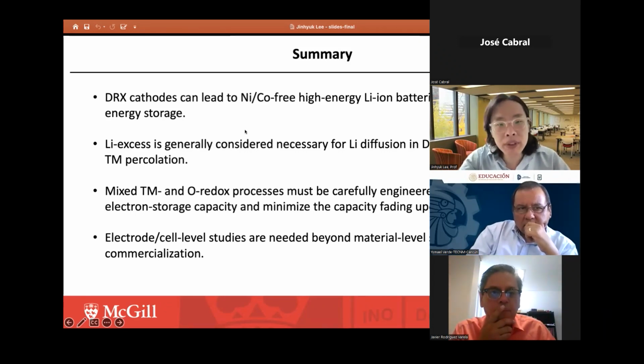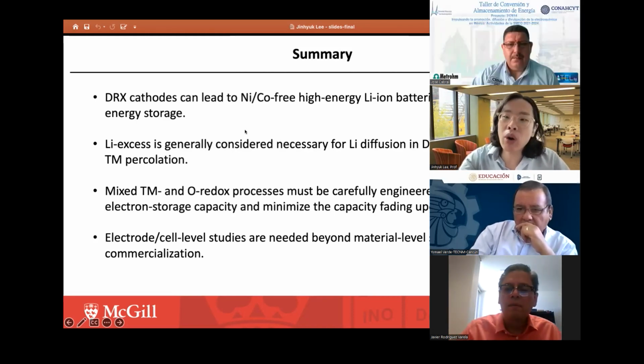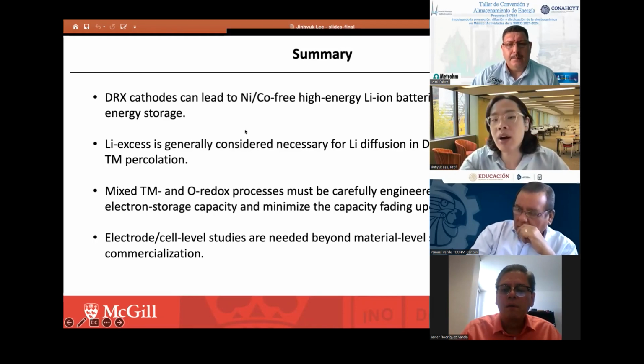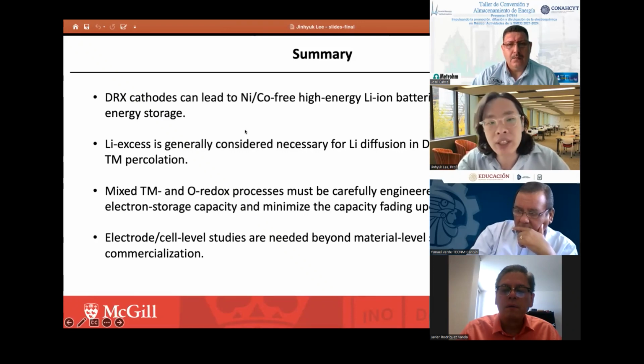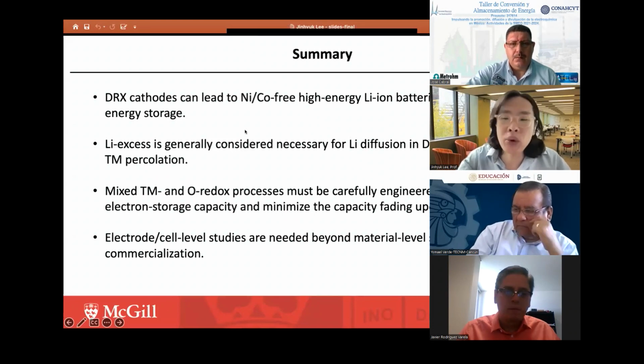I really need to see what composition you're talking about to make any clear statement. But based on your statement, if you generate oxygen vacancies, that means somehow your structure is reduced. When we talk about the oxidation process of the existing oxygen, an oxygen vacancy does not have an oxygen ion there, so there's nothing to oxidize at this particular site. But that's a good question, though I have no clear answer about it.